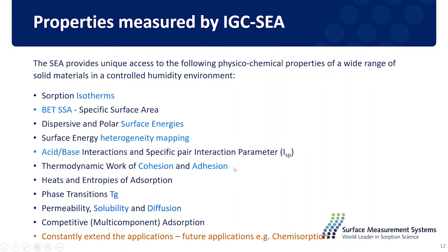And in the case of formulation studies for composite material, it's very useful to calculate the work of cohesion and adhesion between different components, which really comes from the surface energy of each individual component. And I do have a case study in a later section introducing the work of cohesion and its application for composite materials. And also by varying the temperature as well as the flow of the carrier gas, we can calculate some other properties of the solid material, like the glass transition temperature and humidity, as well as the solubility or the diffusion of the material.